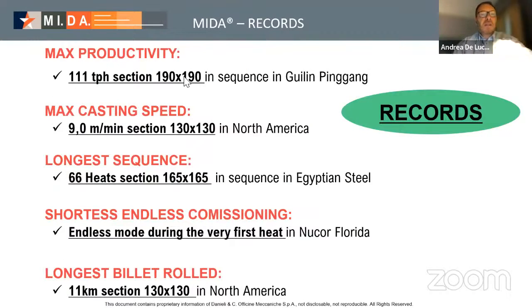Some records in Guilin Pinggang, China: one single strand caster, which is the core of the technology, reached 111 tons per hour. The maximum casting speed, the continuous casting speed, is not a peak of 1 or 2 seconds. This speed is held 23 hours continuously during the day, 9 meters per minute with a section of 130 by 130 millimeters.